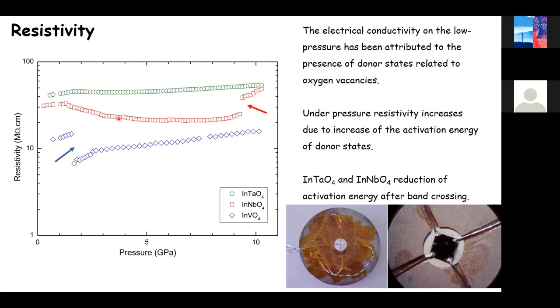And we observe the phase transition in indium niobate, which is also expected around 13 GPa. And in indium tantalate, which is expected at even higher pressure, it is not seen in these experiments. We only see this gradual behavior of the resistivity with no discontinuity in it.